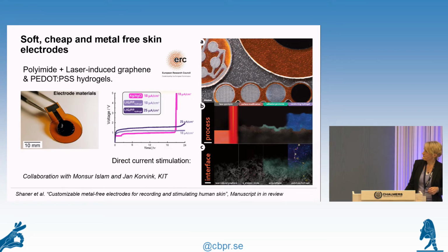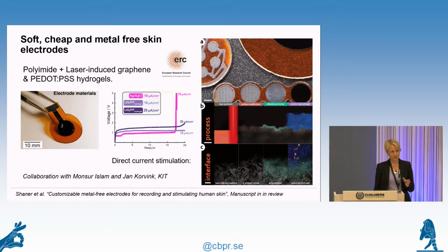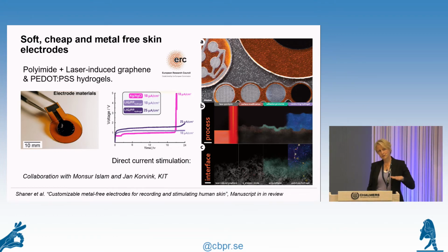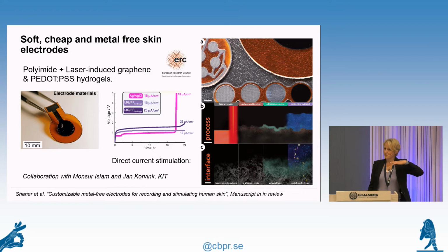So to make this possible, we connected to colleagues at the Karlsruhe Institute of Technology, and they taught us this cool process. So we actually use the same kind of polymer material, polyimide, and then we take a laser and pyrolyze part of this polyimide material into conducting carbon. So it's going to be a graphene-like material, and on this graphene-like material we then print a conducting polymer hydrogel electrode, which means we can make a complete electrode just made of polymeric materials that can be made super cheap.